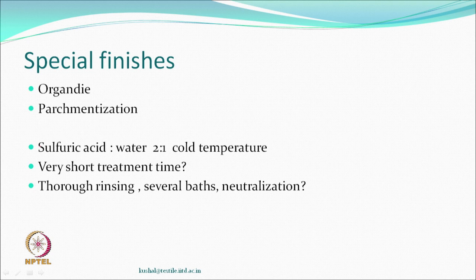It is a very interesting process and a very delicate process, and it is very, very critical that you control the parameters very nicely, otherwise things can be very dicey. And what do we do? We do sulfuric acid treatment. If you remember, 75% weight by weight sulfuric acid, aqueous, can dissolve cotton, right? So you are taking something like 2:1, which means about 66% or so. So it won't dissolve the cotton by itself, but it's concentrated enough to do a lot of damage, right?